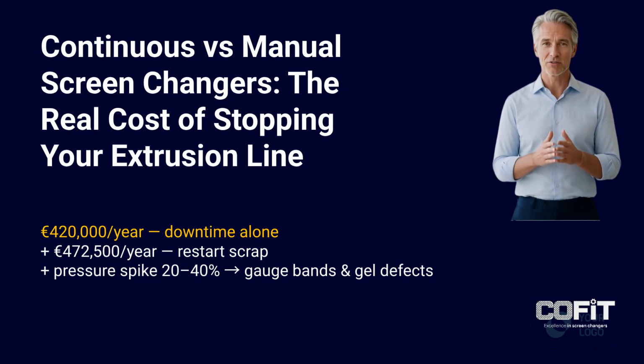Each restart generates transition material, product made while melt pressure restabilizes after the screen change. On quality-sensitive film grades, this material falls outside specification and is scrapped or downgraded. And during the screen change itself, the melt pressure spike, typically 20 to 40% of operating pressure, propagates through the die and into the product.